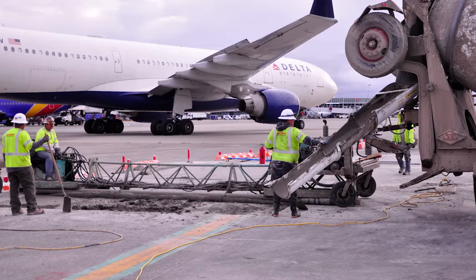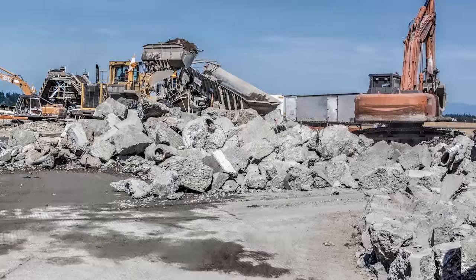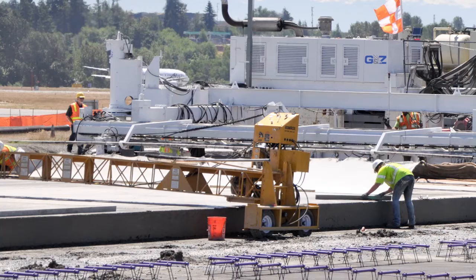And no wonder. SeaTac is now the 9th busiest airport in the country, with over 412,000 takeoffs and landings in 2016 alone. With projected growth to service 65 million passengers per year by 2023, the runways must be concrete tough. The new runway pavement profile is 8 inches of crushed recycled concrete and aggregate subbase, 4 inches of asphalt, and 18 inches of cast-in-place concrete in 4,000 panels over its 1.78-mile length.